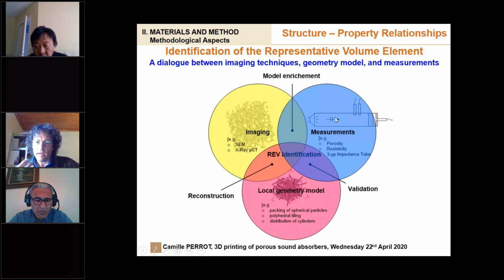Basically, the validation step should be independent of all the previous key steps, imaging techniques, and the candidate for a representative elementary volume, so that you can compare macroscopic properties or transport parameters which have been measured at macro scale with macroscopic properties which have been obtained in an independent way, just by solving the boundary value problems I introduced briefly previously. And if the agreement is good, then you have this representative elementary volume, and you can go further into the optimization process.